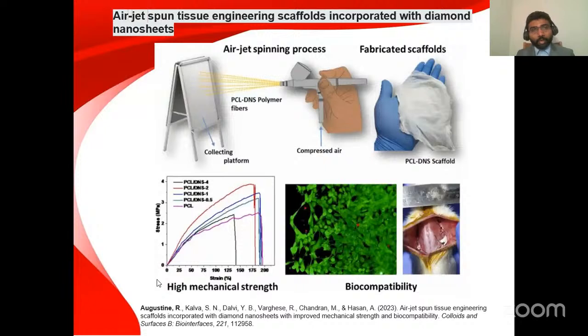And also we developed a new approach, that is air jet spinning, using high pressurized air. We drive the polymer from an airbrush to a collector, and then we collect the fiber in a similar way to electrospinning. This is a relatively new approach. We did a lot of optimization to achieve this, and in one of the studies which is published, you can refer to this paper. Because of the time limit, I am not going into detail. You can refer to this. This is an interesting approach.